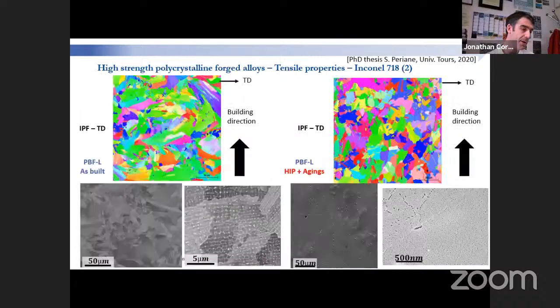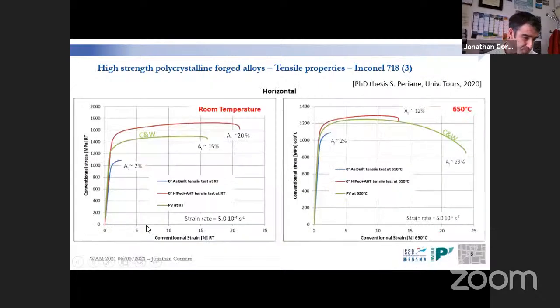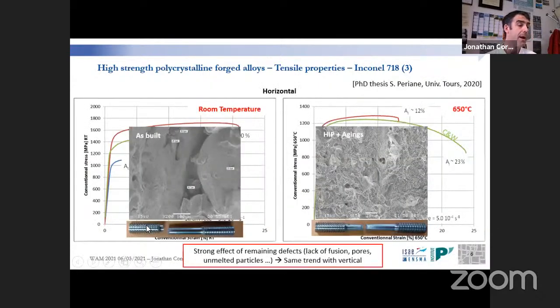And this is something we can already understand with this kind of observation here, where you can see lots of variation in contrast at the grain scale, being an indication of the high dislocation density we have. So, okay.